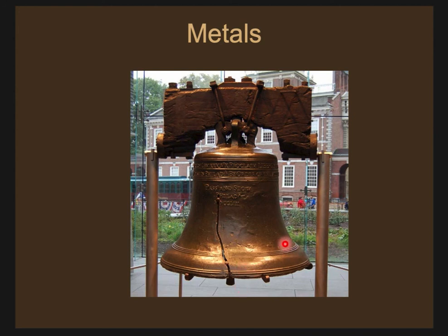Now, what scientists did is they tested the metal from different parts of the Liberty Bell. And what they found is that the proportions of the bronze were different in different sections. That is, this was not homogeneous and it was not uniform. Now, what does that mean? It means that different crucibles were used to pour in the bronze.